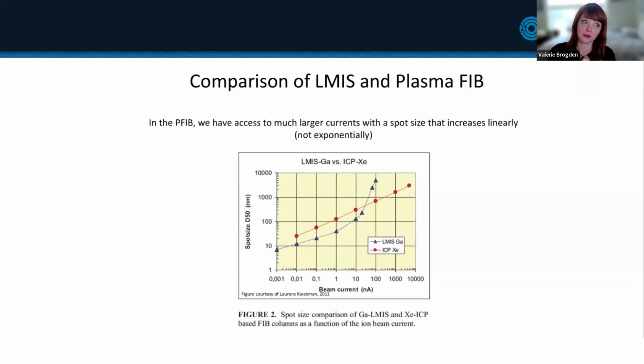Also, a lot of people have access to PFIBs that have different ion species. Xenon is obviously the most popular, but more and more we're seeing ion species like oxygen and argon in the tool. So when you're using argon, you can kind of think of it as chipping away with smaller ions. So it's kind of a sandblasting technique rather than just throwing baseballs at your sample.